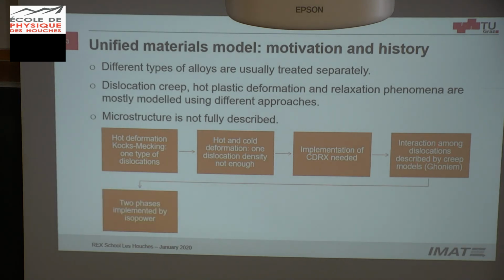So we introduced this, and of course we introduced the two phases for titanium alloys in an isostrain way. What is missing are heterogeneities, texture, and geometric dynamic recrystallization. With all this, we want to use the same internal variables, which are dislocation densities, subgrain sizes, grain sizes, particles and so on.